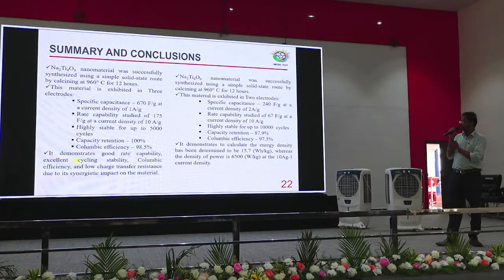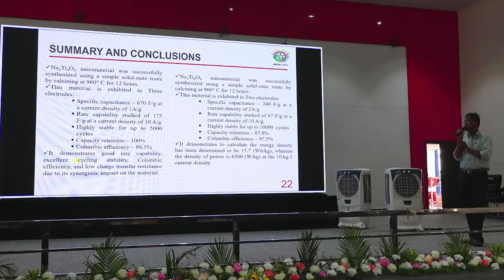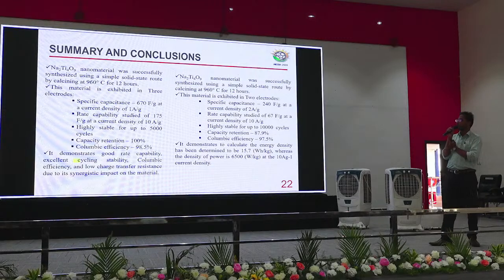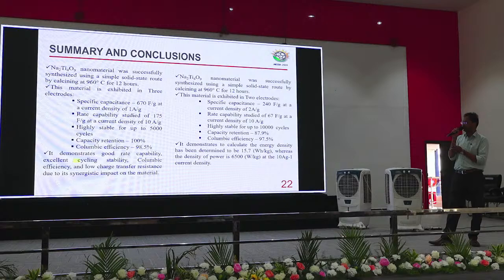So this is my summary. First, we synthesized my material by the solid state route, calcination at 960 for 12 hours. So for this three electrode device, we have capacitance around 670 farad per gram, and rate capability studied around 175 farad per gram at a current density of 10 ampere per gram, around 5000 cycles. They get capacity retention of 100% and Coulombic efficiency around 98.5%.